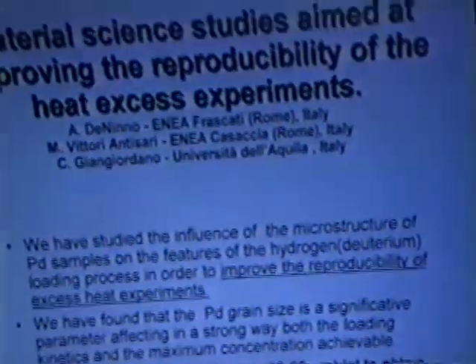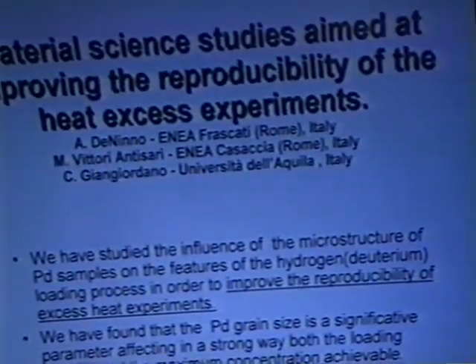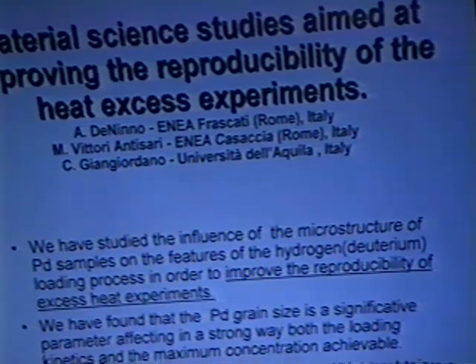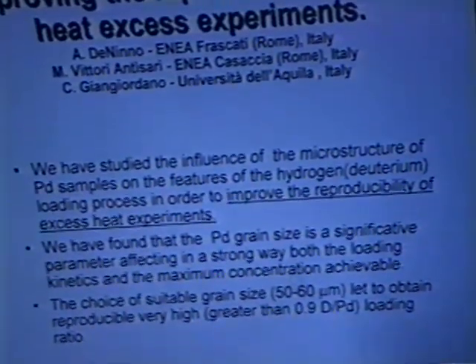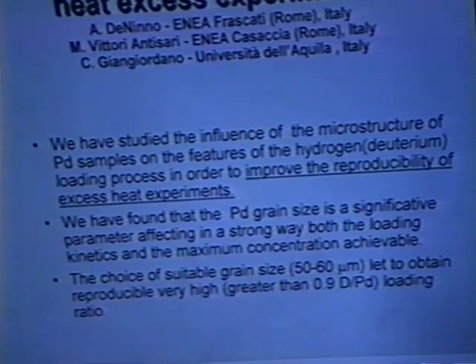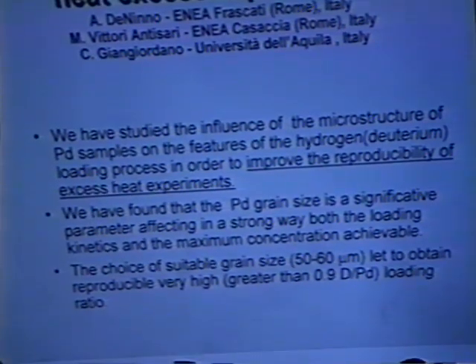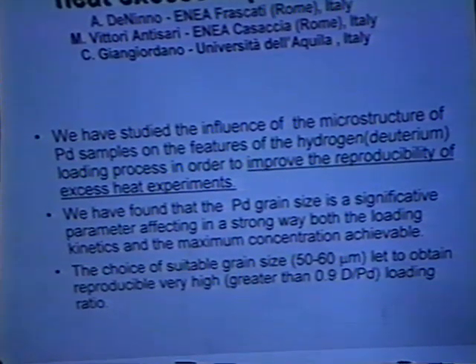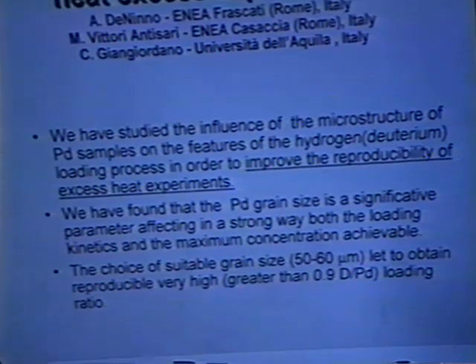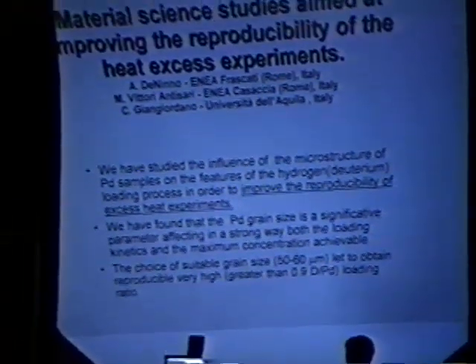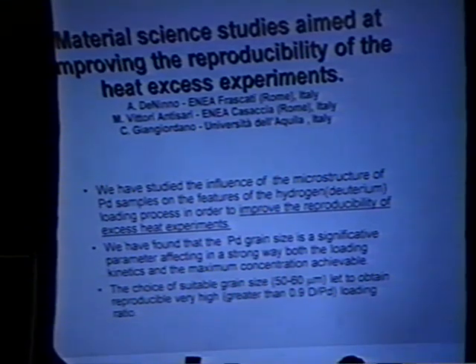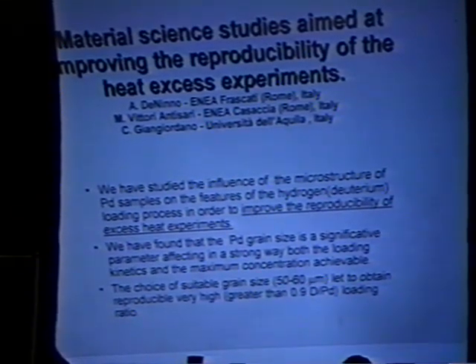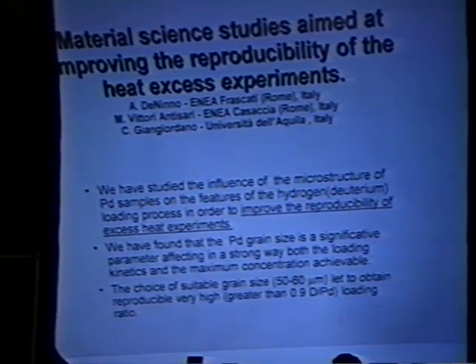We have found that the grain size is a significant parameter to improve the loading ratio, and then the probability of having a successful heat excess experiment. The best range of grain size is between 50 and 60 microns. This led us to obtain, in a very reproducible way, high loading ratio, I mean over 0.9 D on Pd.